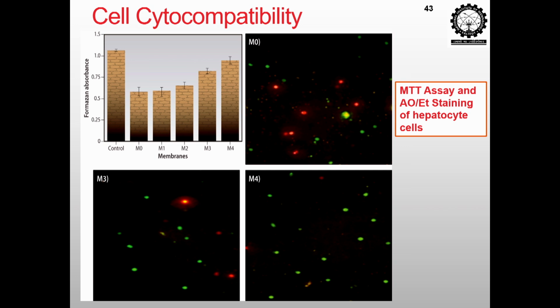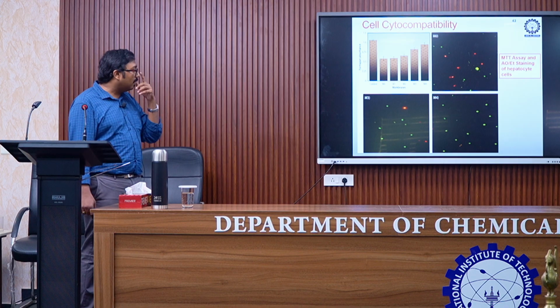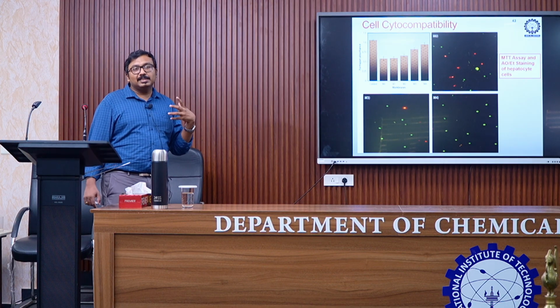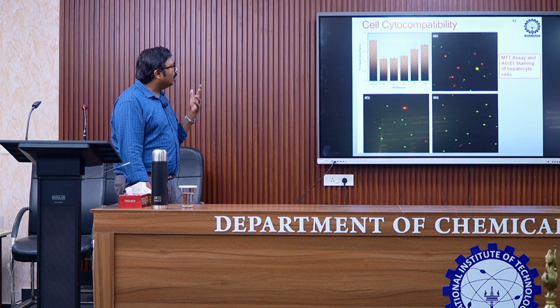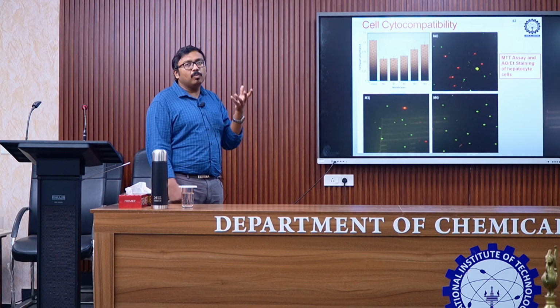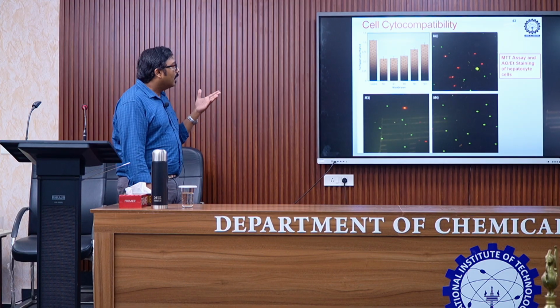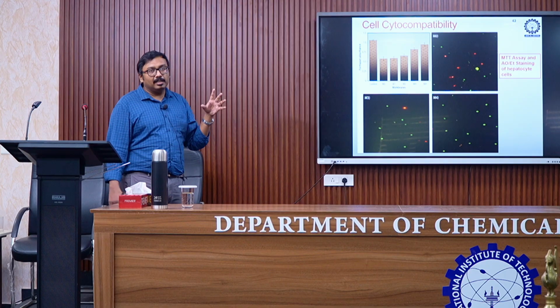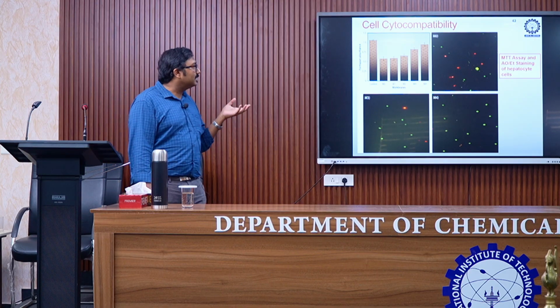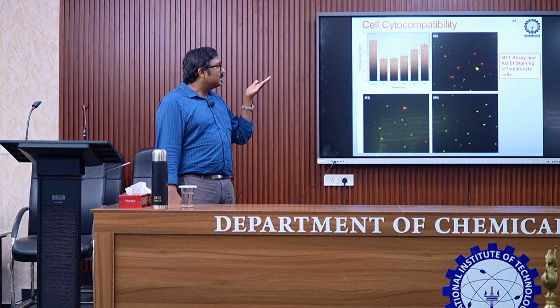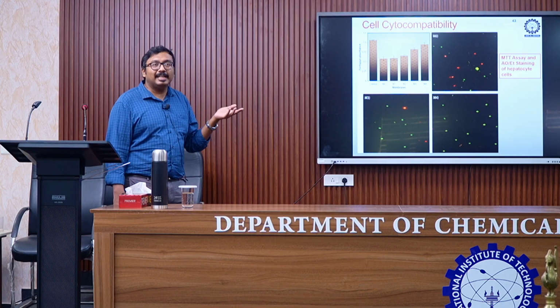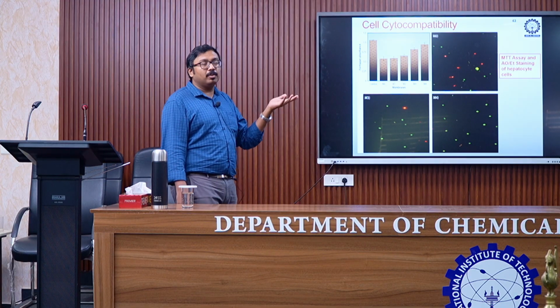Another thing done was the cell compatibility. Ideally, no other cells except blood cells come in contact with the membranes, but this was just done to understand whether cell adhesion takes place. There is not much cell adhesion, and we don't want cell adhesion, in fact, but whatever adhered did not die. So both of these were positive results that would say that the membranes have cytocompatibility, but it cannot be used as a platform for growing cells.